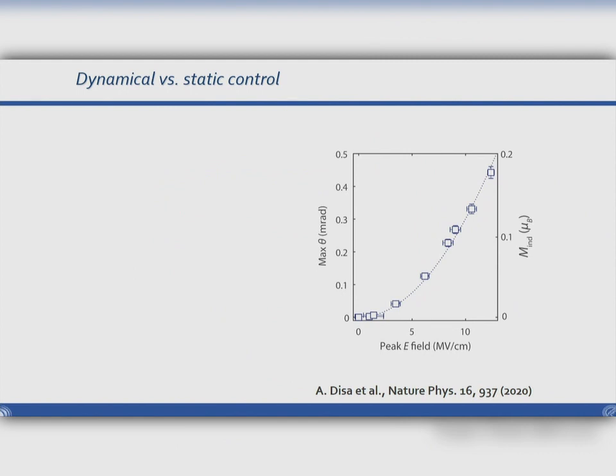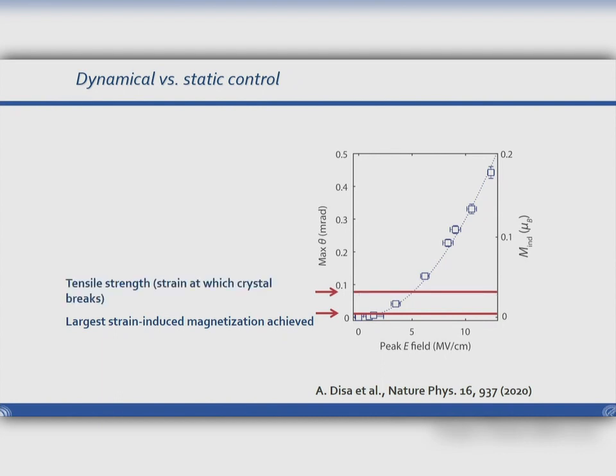Okay, so how can we now compare this approach of dynamical structure engineering with what people have done before, which is applying strain? First of all, the largest strain-induced magnetization achieved in this compound was of the order of 0.05 μ-Bohr per unit cell. In our experiments, we were going far, far higher here. So in principle, even the maximum tensile strength that you could achieve in a sample that had ever been observed cannot reach the highest net magnetization that can be induced in this material.